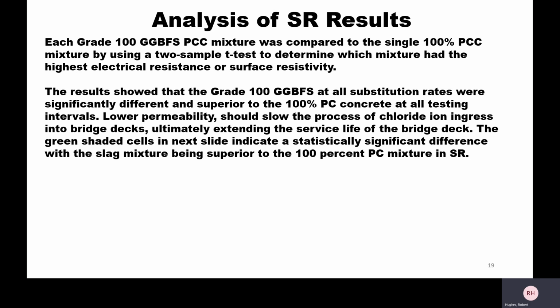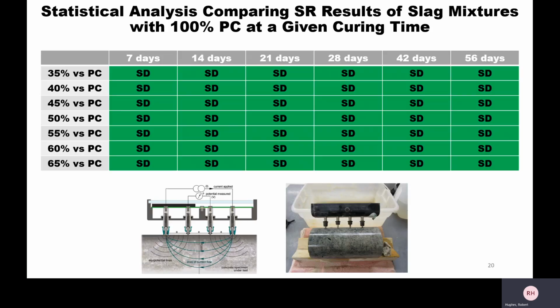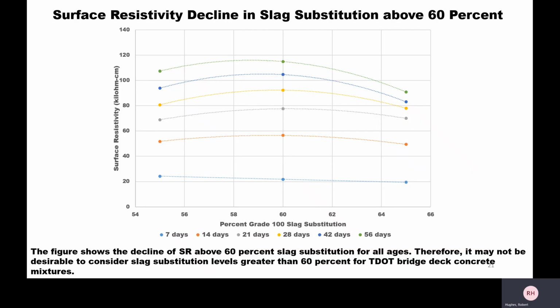Now, the green shaded cells in the next slide indicate a statistically significant difference, with the slag mix being superior to the 100% PC in SR. You can see that here. Every scenario at every testing date is significantly different and superior. And this is a graphical representation of our SR that I was talking about earlier. You can see here our peak at 60%. So this points to, for the probable use of a TDOT Class D mix, maybe 65% is not the best idea. Anything 60 and less is more optimal for permeability reasons.